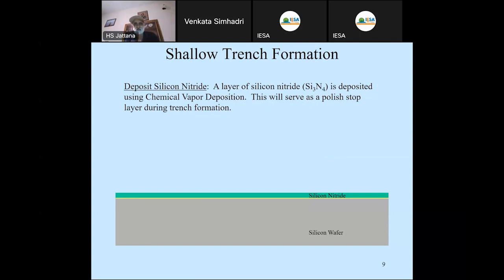And as you can see, the thickness of silicon nitride is 4 to 5 times that of the base oxide. If it's 100 angstrom, it's 400, 500 angstrom. The silicon nitride layer is deposited, and the way is CVD, chemical vapor deposition. It can be atmospheric, it can be PE, it can be LPCVD.